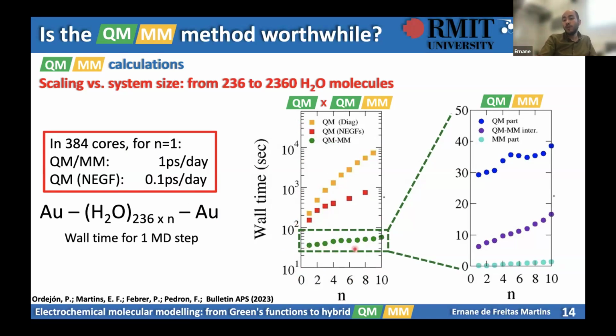But if you do this with QMMM, in this case we are increasing only the amount of MM atoms. That's basically costless. So we can have nearly the same cost as having 10 times fewer water molecules. And if you split these contributions, you can see that the MM part is not representative. What that means is, with QMMM, I can have 1 picosecond per day for this particular system. That means 1,000 steps.